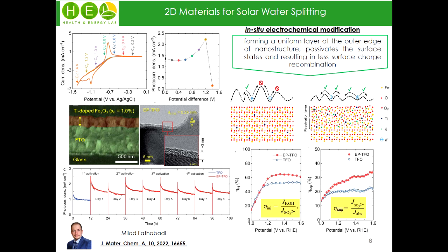With this passivation layer, we could have a very stable photoanode, at least for nearly 100 hours. And we had improvement in injection and separation efficiency, and also more uniform potential on the surface.